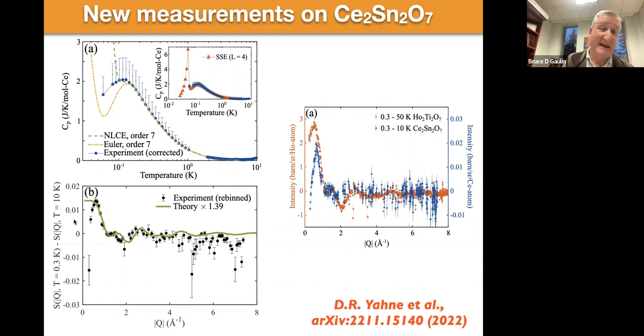And then we could go out and measure the diffuse neutron scattering in cerium stannate. And actually, this is quite interesting. So this is the low Q, what you might think of as magnetic diffuse neutron scattering from cerium stannate, as measured in a powder. And it's a temperature difference measurement, 0.3 Kelvin minus 10 Kelvin. So this is the data. And on the basis of the microscopic Hamiltonian estimate that our theory friends get from fitting this high temperature heat capacity data, they can calculate this diffuse scattering, which doesn't agree perfectly, but it actually is a pretty good description of our experiment, even on an absolute scale to within 40%, which I think of as pretty good.